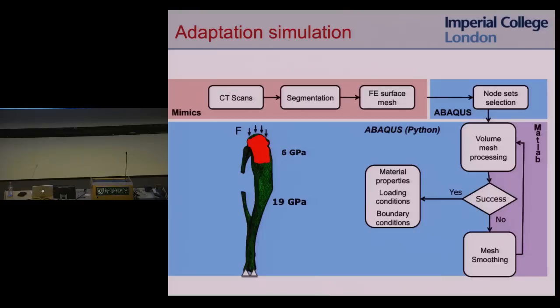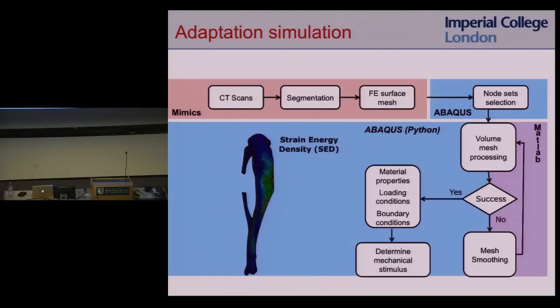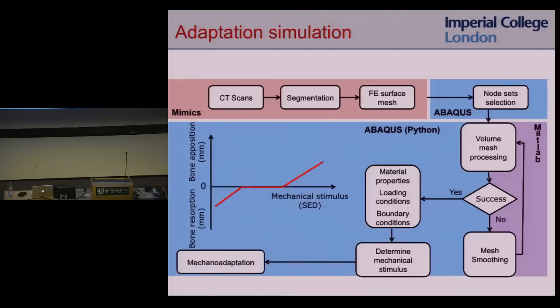We then create our material properties. We use very simple material properties, homogeneous isotropic material properties for the cortical bone and the trabecular bone, which is this region up here. And we applied our loads. We then determined the mechanical stimulus. So in this example, I'm going to use strain energy density as a mechanical stimulus because that's often what's been proposed in the literature. We then used a mechanoadaptation rule, which says if that mechanical stimulus is high, you grow the bone. If it's low, you resorb the bone, you get rid of the bone.